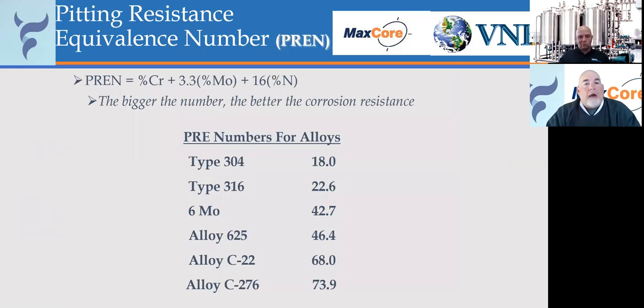You can also calculate the pitting resistance of an alloy by the chemistry. There is a number known as a pitting resistance equivalency number, or PREN. You calculate that by the percent of chrome plus 3.3 times the percent of molybdenum plus 16 times the percent of nitrogen. By doing that calculation, the PREN number for 304 stainless steel is 18, for 316L it's 22.6, and six moly alloys are at 42.7. Your nickel alloys, like alloy 22, are at 68. The higher that number, the better for corrosion resistance and pitting. So that gives you kind of a ranking of the different alloys.